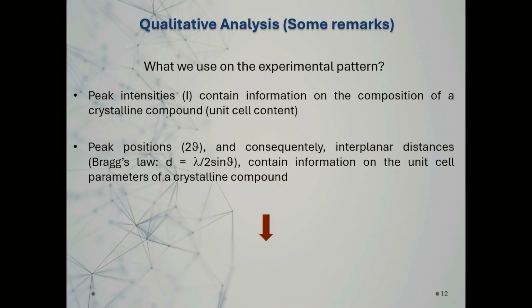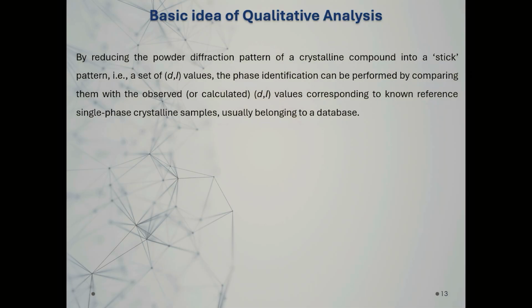So what we use on the experimental pattern when we perform a qualitative phase analysis. The peak intensity contains the information on the composition, so the unit cell content. Instead, the peak position 2theta and the corresponding interplanar distances, which we get from Bragg's law, contain the information on the unit cell parameters.